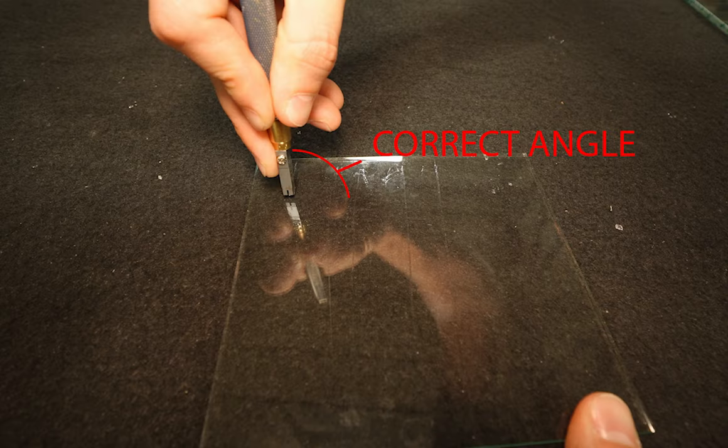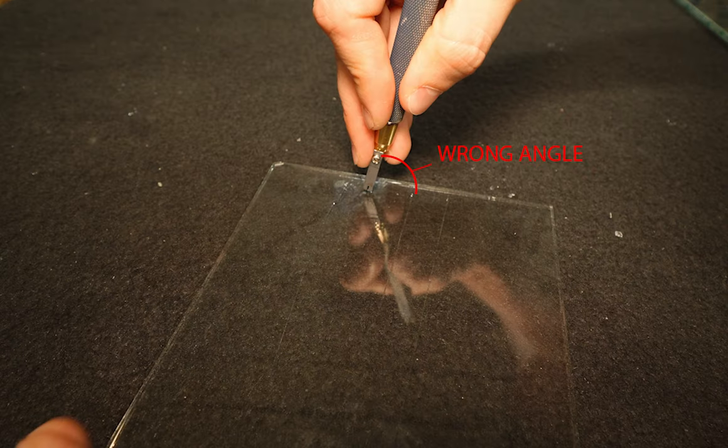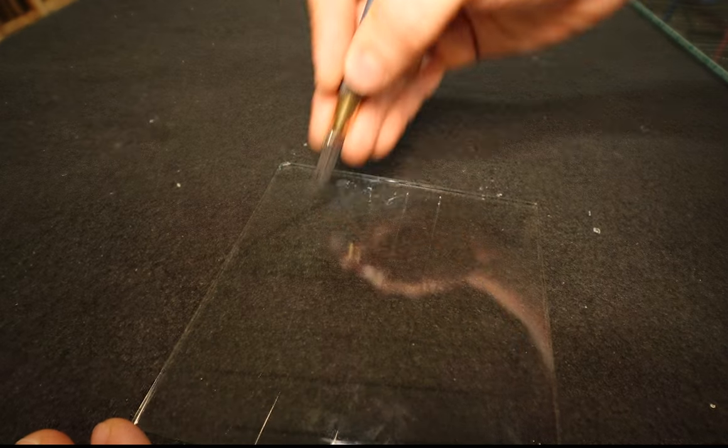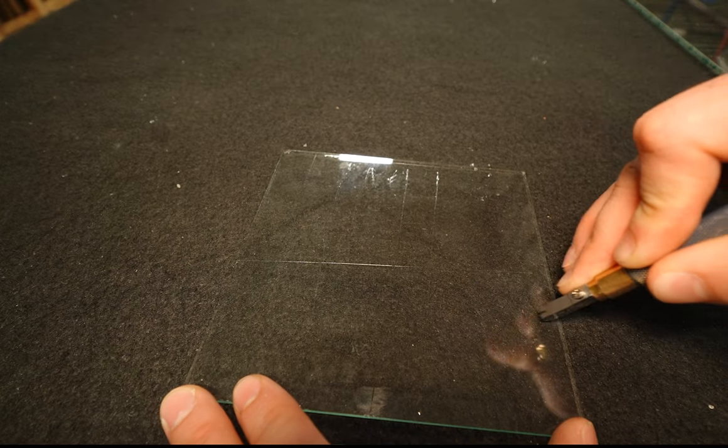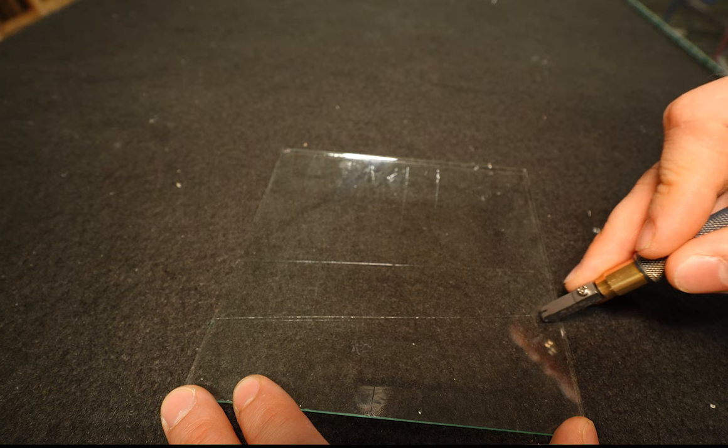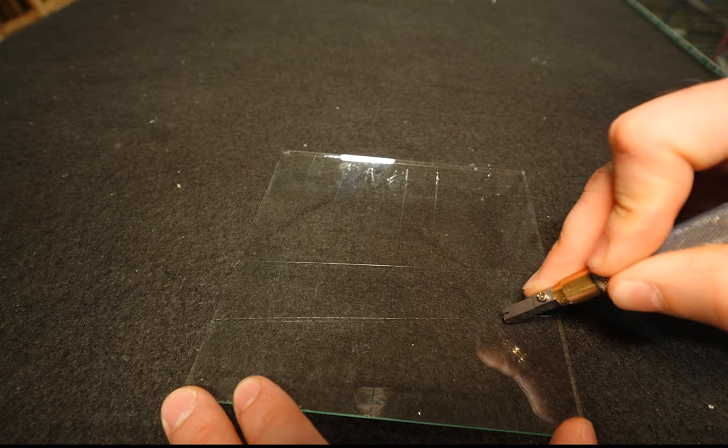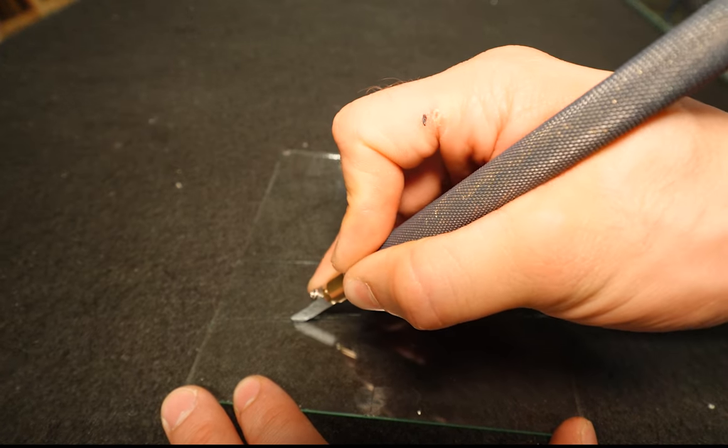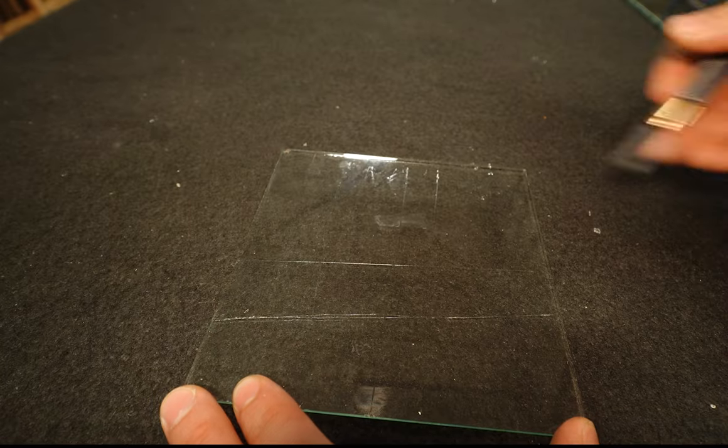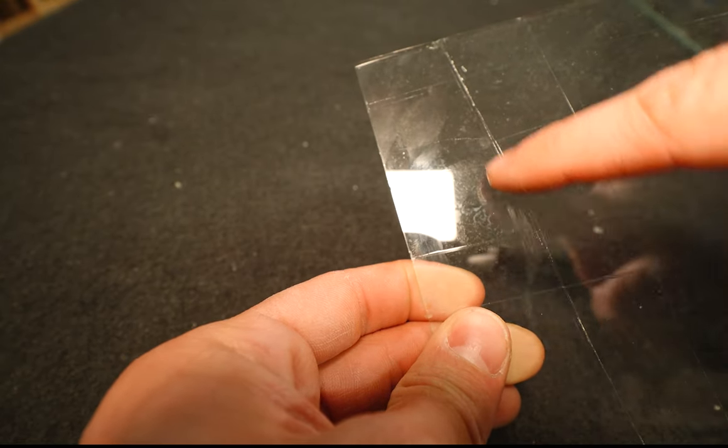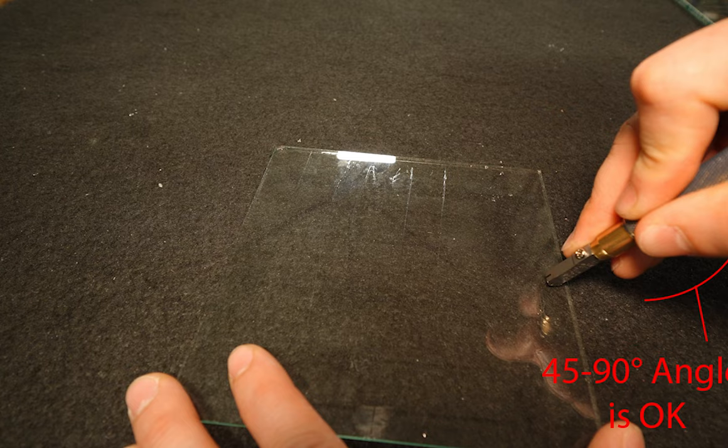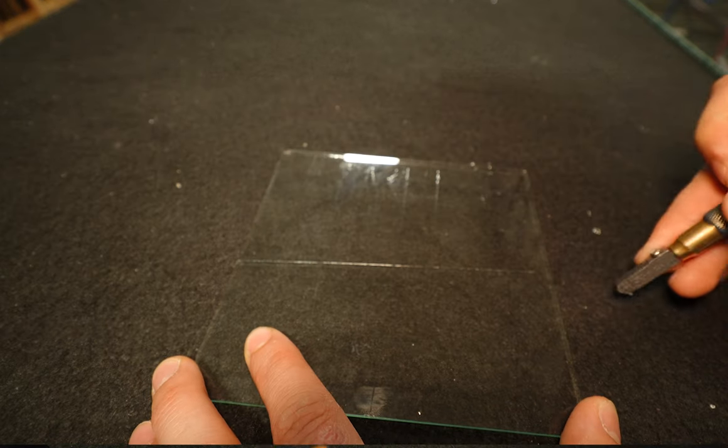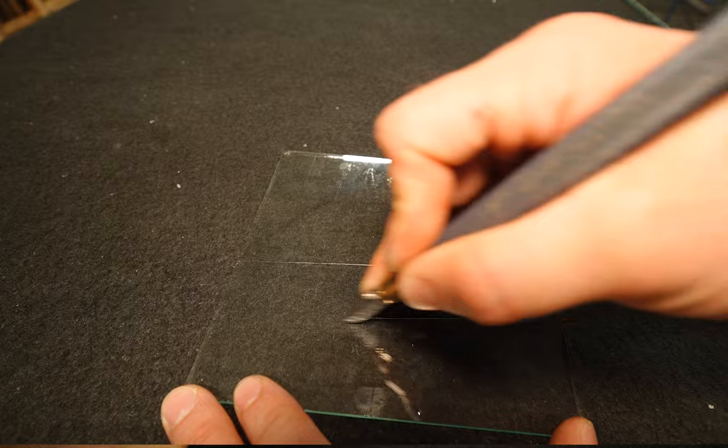General scoring techniques call for the scoring wheel to be perpendicular to the glass. You'll feel the sides of the cutting wheel scrape against the glass disrupting the score line. You want to score the glass only a single time and not go back over your score line because the glass will have an equal chance of breaking along one or the other and it's impossible to control which line it will break on. You can hold the glass cutter at a slight angle to the glass just as long as the cutting wheel is still perpendicular to the glass.